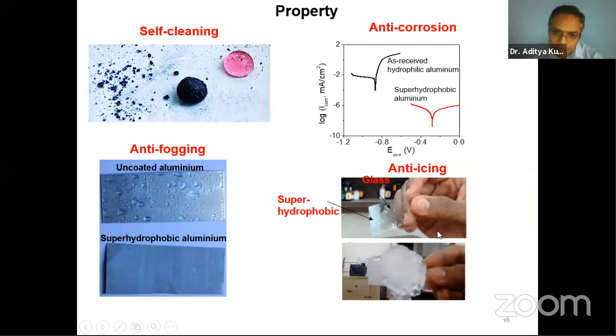In this experiment, they have coated a glass surface. In this part, you can see this is the glass side and this is the coated part. And we put ice on both parts. What happened? Ice accumulated onto the uncoated part, not over the coated. So because of this super hydrophobicity nature, the surface also shows anti-icing nature.